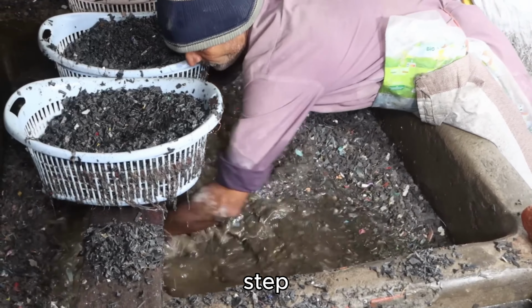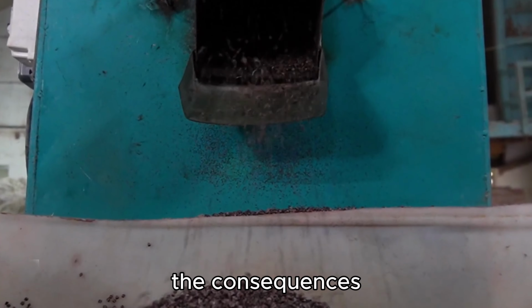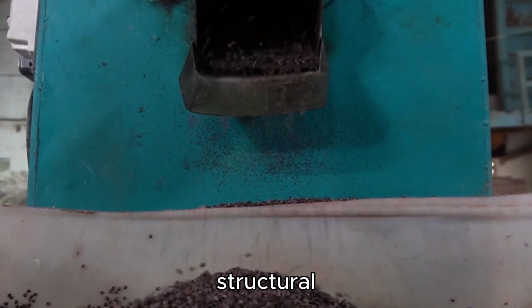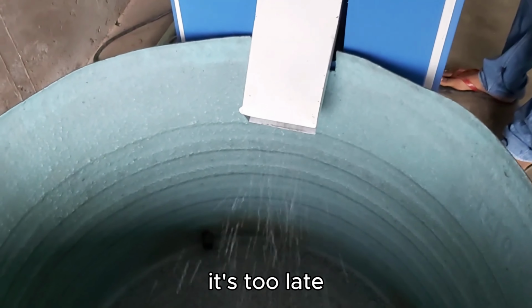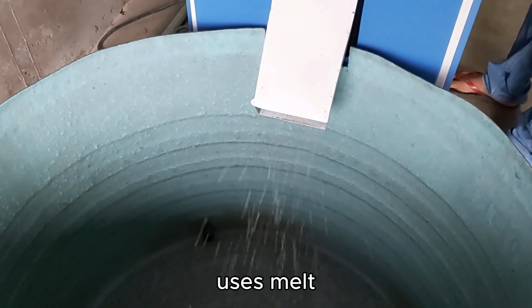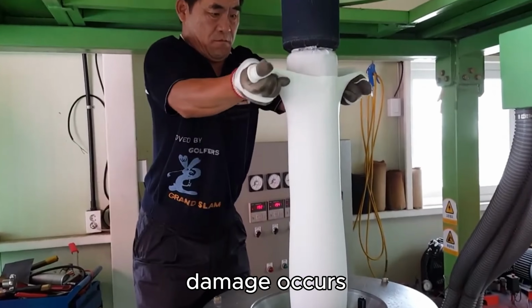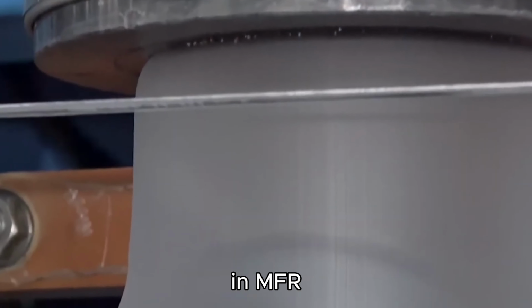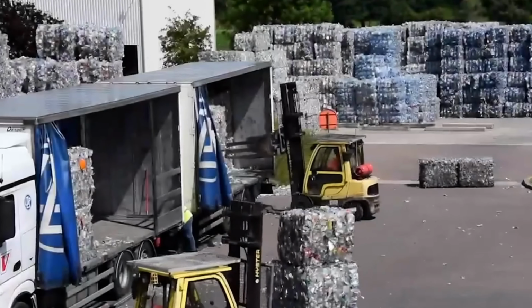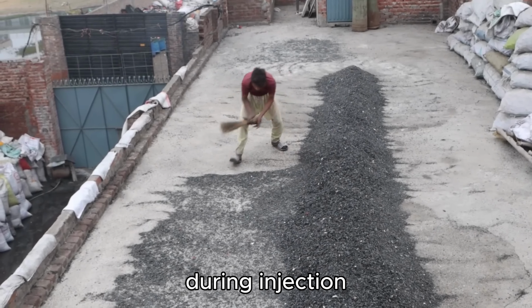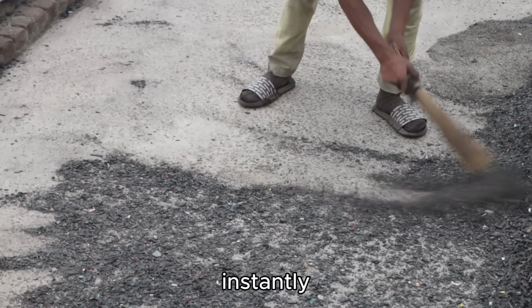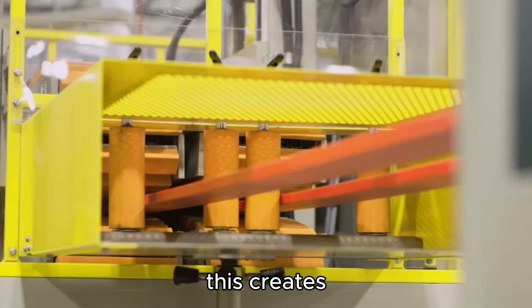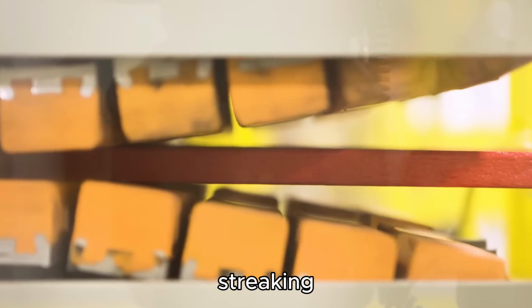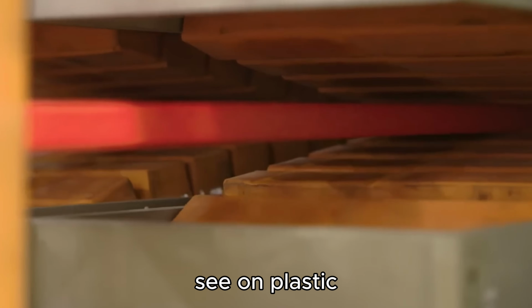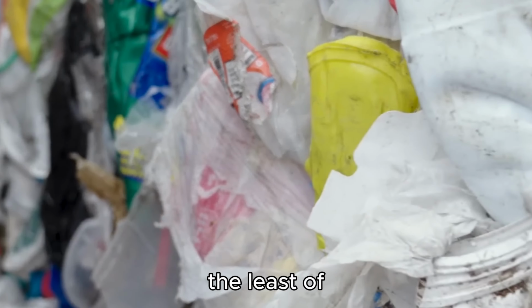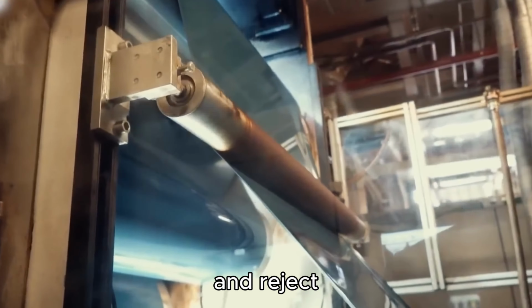So what happens if you skip this step or don't do it properly? The consequences range from cosmetic defects to complete structural failure, and they often don't show up until it's too late. Industry standard testing uses melt flow rate measurements. When moisture damage occurs, you'll see a 40% increase in MFR, indicating polymer degradation. When moisture-laden plastic is heated during injection molding or extrusion, the water instantly vaporizes into steam. This creates what's called splay or silver streaking, those unsightly lines and marks you sometimes see on plastic products. But splay is actually the least of your worries because at least you can see it and reject the part.